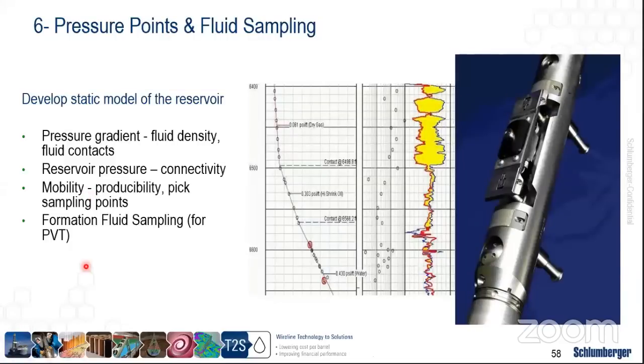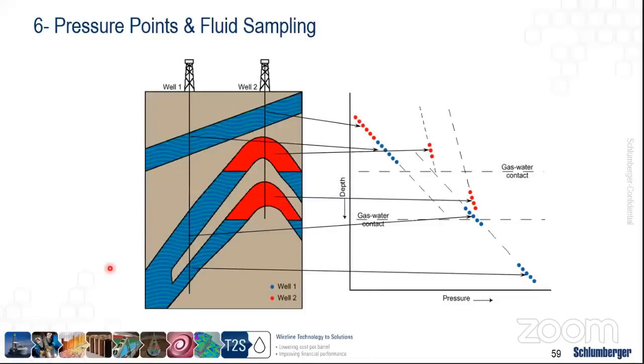On top of that, we can also acquire downhole fluid samples for PVT analysis, for pressure, volume, and temperature, in order to understand the type of fluid or hydrocarbon that we have in place. So as I said, we can look at the gradients from different wells at different reservoirs, where typically the pressure points are plotted as depth versus pressure in a log view. And by looking at the gradients, we can identify the gradient of water and the gradient of gas. Through the intersection between the water gradient and the gas gradient, we can identify the gas water contact in this reservoir.